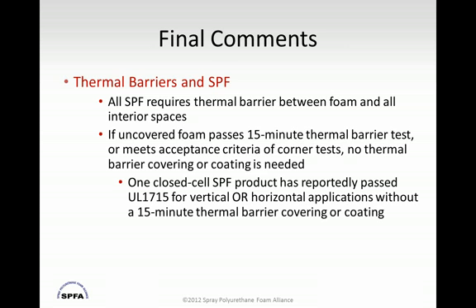If an uncovered foam can actually pass a 15-minute thermal barrier test or meets the acceptance criteria of these large-scale corner tests, no thermal barrier or coating or covering is needed over the foam. Again, I've only heard of one foam that's reported to have passed a UL 1715 test, either for a vertical application or for a horizontal application, without a 15-minute thermal barrier covering or coating. There's only one. This foam has some special additives in it, but generally speaking, very few spray polyurethane foams will pass without a thermal barrier.